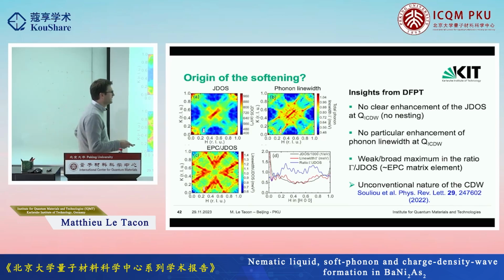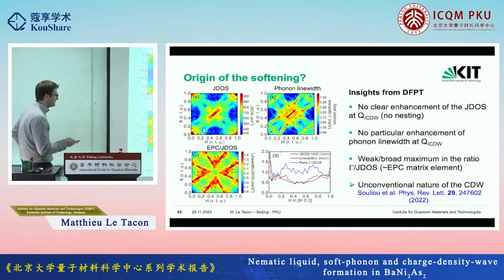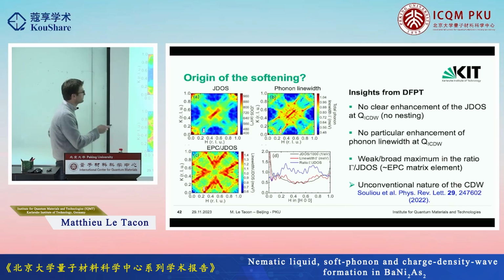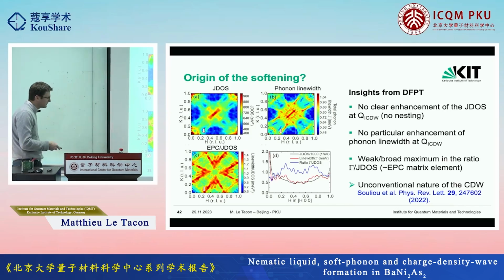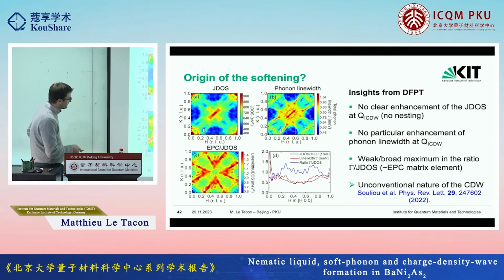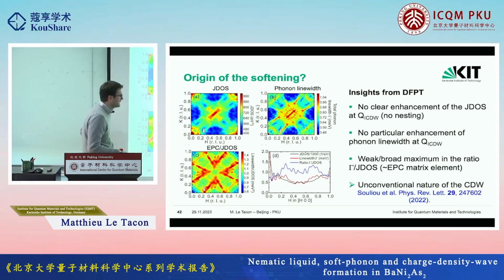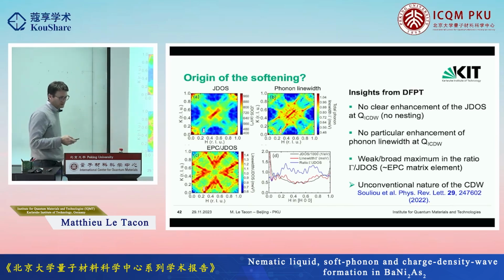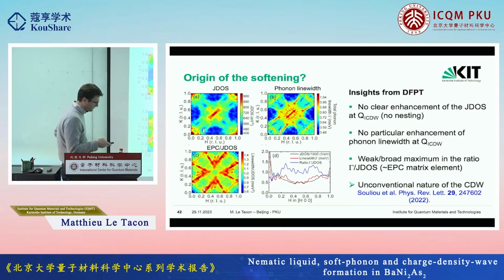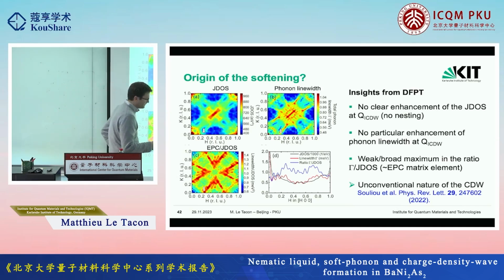And you can look at the electron-phonon matrix coupling element and the anisotropy of the element by taking the ratio of these two quantities. And again, here you do have some kind of maximum, but it's a very broad maximum, very shallow, and it's not particularly remarkable in this direction. I mean, if this would cause an instability, why not this, why not this? There could be instability all over the place. So, long story short, it doesn't look like the electron-phonon coupling in this particular system can be the driving force for the charge-density wave, which we believe has a different nature.